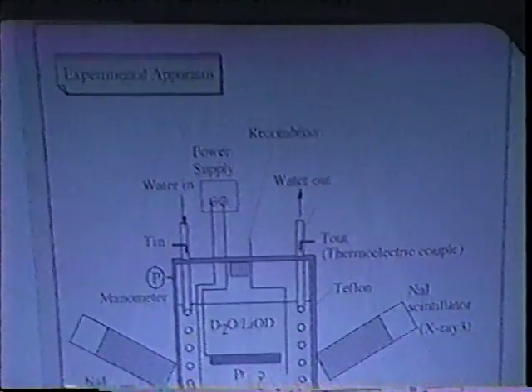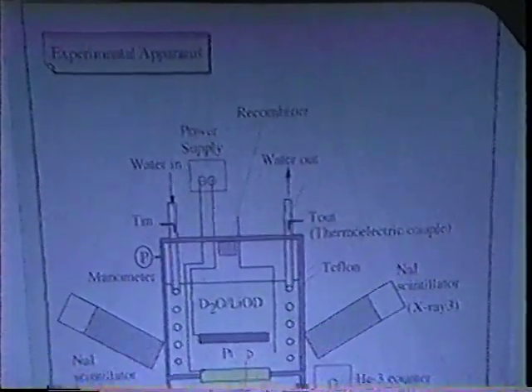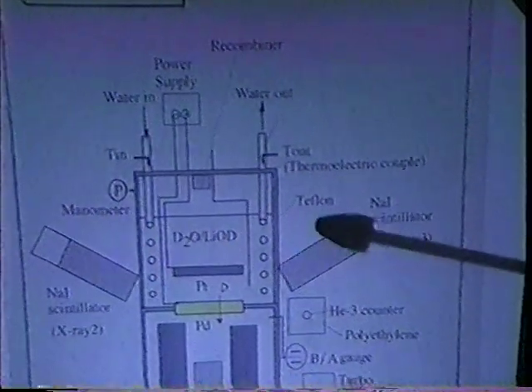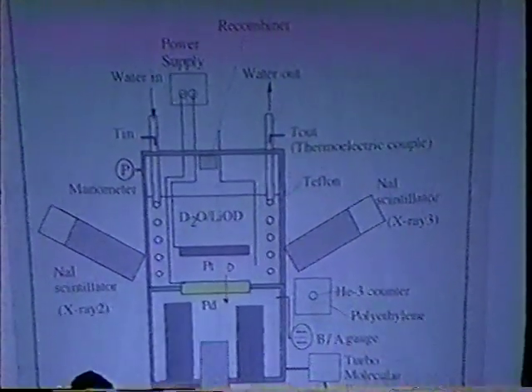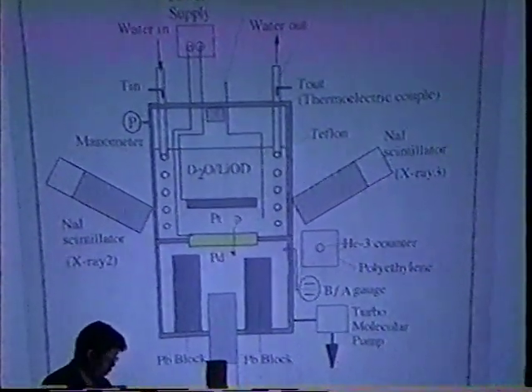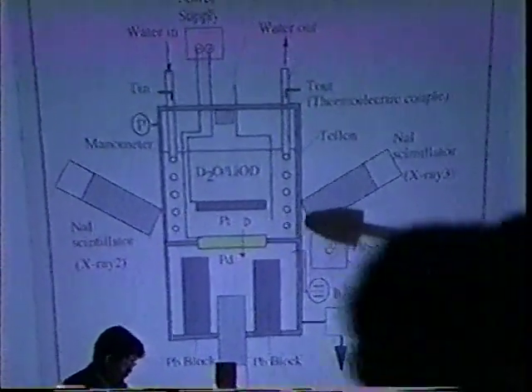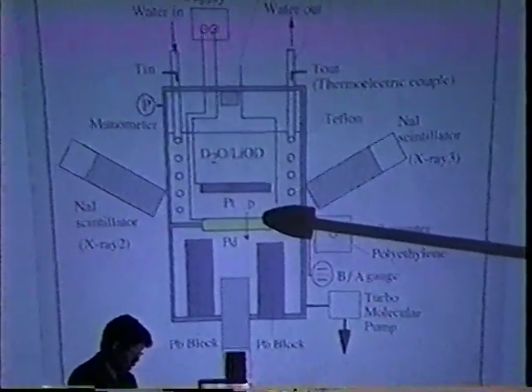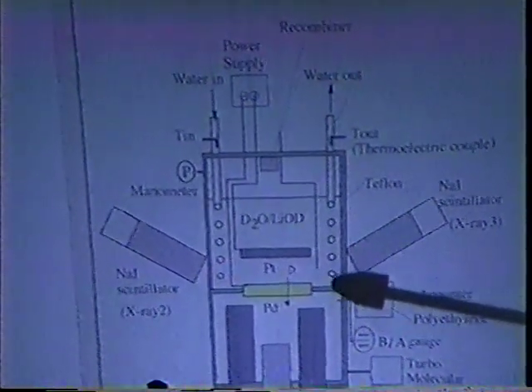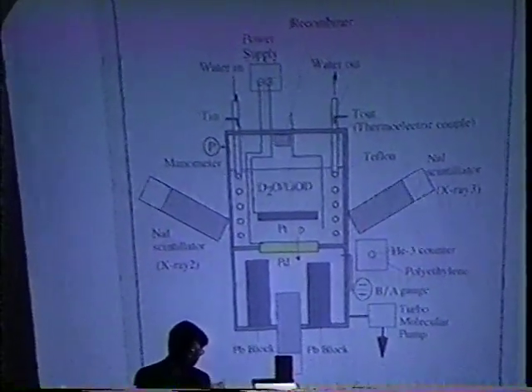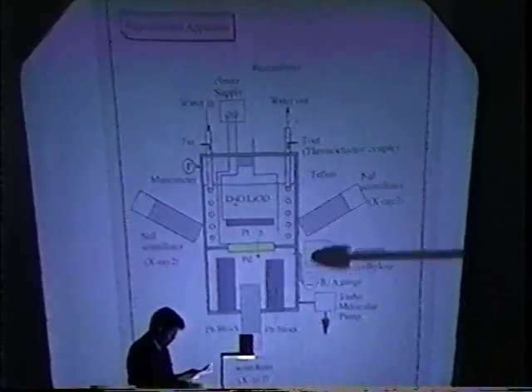This figure shows the cross-sectional view of our experimental system. It consists of two parts, an electrochemical cell for calorimetry and a vacuum chamber for nuclear measurement. Deuterium atoms are loaded by electrochemical potential into the upper side of the palladium sample and released out from the lower side. Therefore, there exists continuous flow of deuterium atoms through the palladium. Excess heat is estimated by flow calorimetry. As for nuclear measurement, 3 X-ray detectors are equipped and 1 neutron detector.